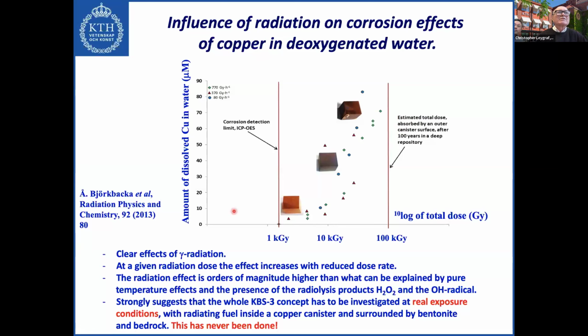Okay, yeah. So on average, if we take any dose rate here, we see that there is a tendency that the corrosion or the dissolution of copper is lower at a certain dose rate and a given dose. So it's not a clear tendency, but there is a tendency. You see the blue ones here are the dose rates, the lowest dose rates. They are up here and up here and up here. They seem to be giving a higher corrosion at a given dose. But again, the trend is not absolutely clear, but there seems to be a trend like that too.